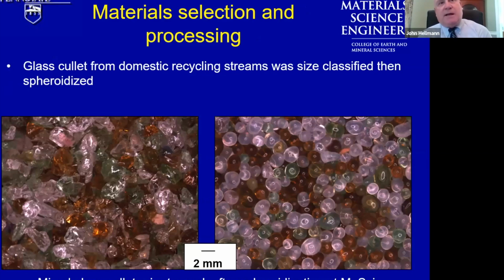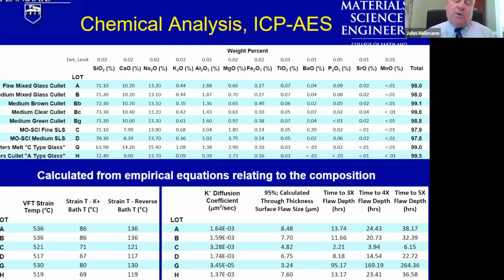So we procured glass cullet from the domestic recycling glass industry. This is glasses of a variety of colors, all from your beverage containers and the like. So you'll see green, you'll see brown, you'll see clear, occasionally even blue. We worked with MoSci then to sphericize these using their flame spheritization processes. We characterized their chemistries, which was an important thing because we needed to know how to ion exchange the materials to different levels of starting flaw depths. So we used this information to calculate things like strain temperatures and temperature-time behavior necessary to embed a compressive stress field at a depth of 3, 4, and 5 times the initial starting flaw depths.